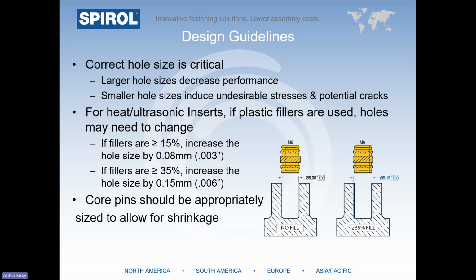It's also important to emphasize that the core pin used to mold in the hole should be appropriately sized to allow for plastic shrinkage after cooling. The hole size should be verified with a plug gauge post-cooling. In summary, it's imperative that a designer perform testing to validate the appropriate hole size for the application, not just rely on the recommended hole sizes we publish in our catalog. Complementary application engineering service SPIROL offers can assist with this sort of testing.